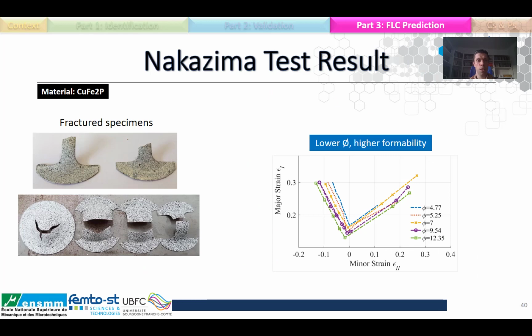To minimize the friction between the punch and the sheet, we use a Teflon strip on the other side of the specimen, while on the punch we apply a generous amount of oil. The photos on the left of the page show the fracture of different geometries. We can observe on some specimens that the fracture doesn't take place in the middle. On the right, we have the forming limit curve we obtain with experimental work.